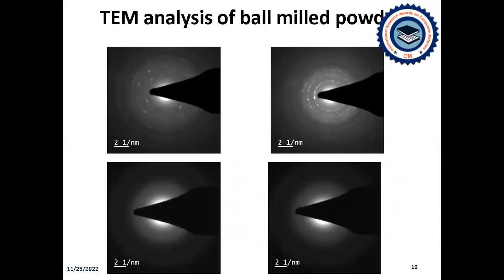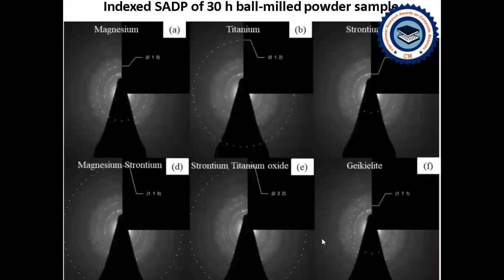When it comes to the TEM analysis, these are the diffraction rings we can observe in the ball milled powder at 30 hours of duration. Minute dots are present on the diffraction rings, which represent the elements present in the ball milled powder. In this diffraction, the rings are too diffused, and it suggests that a partial amorphous structure is being observed, and also the crystallite size reduction to the nano scale regime.